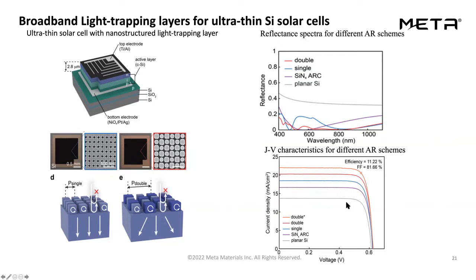What you see on the right-hand side summarizes the structures that we have tested for planar silicon film, which in this case is only 3 micron thick, which is really ultra thin. In this case, we are just looking at the current density. It is as low as 14 milliamps per centimeter square.